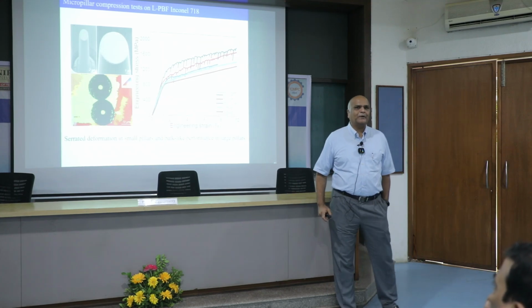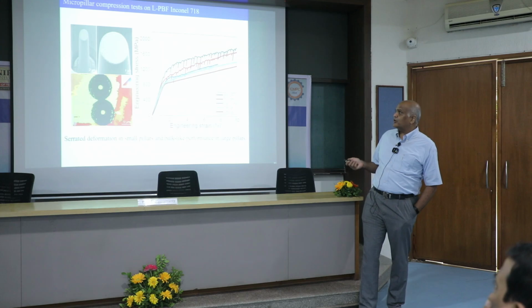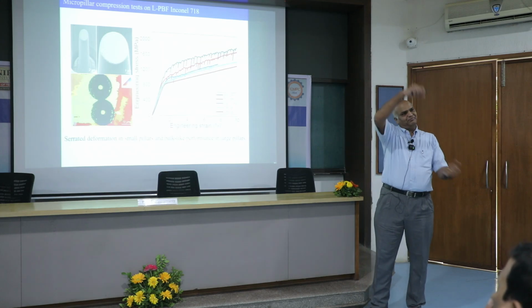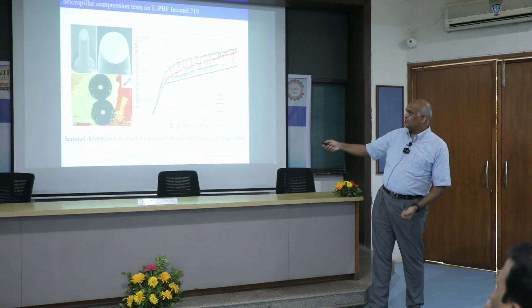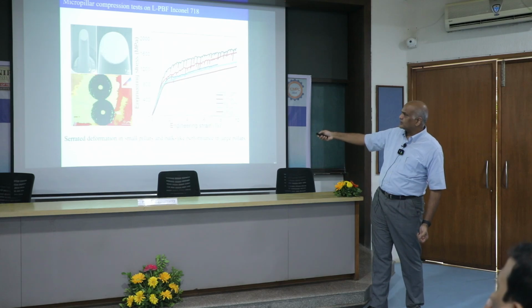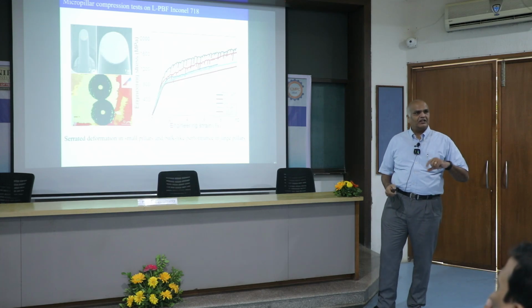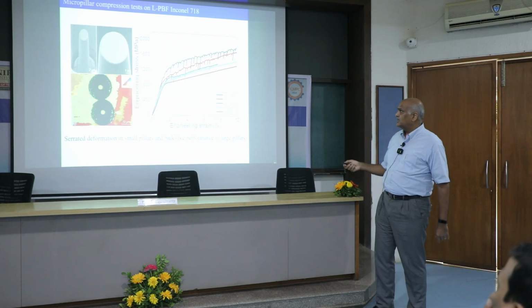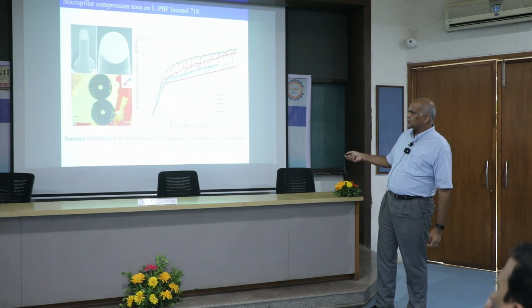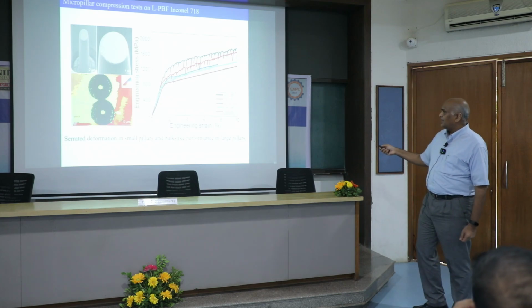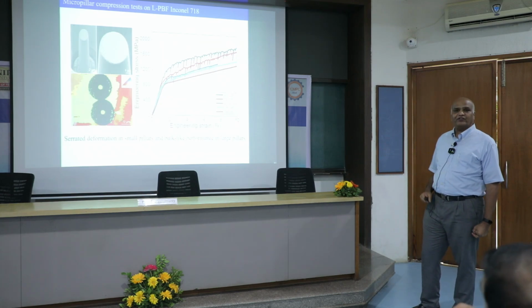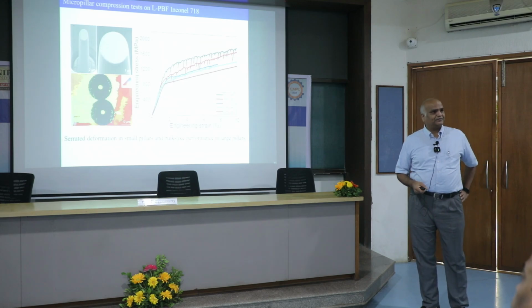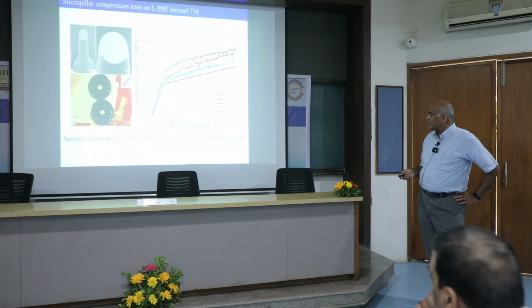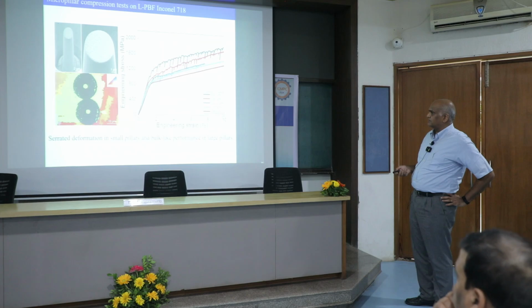What we do is make micropillars, not conventional standard tensile tests. So we make these pillars. This is a 2 micron scale bar, so you can see this is maybe 3 microns in diameter. We machine them with a focused ion beam, and we make sure they are all oriented in the same way. Then we can test this as a function of the pillar diameter, and look at these properties a lot.